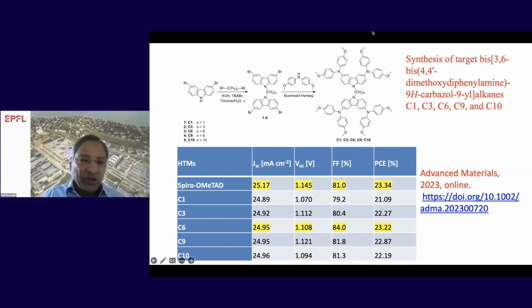That was the idea. So here we have changed the chain length of the two carbazole containing units from C1. The reference sample always gives very high efficiency, 23.34. That's spiro-OMeTAD as a reference sample for us. The C1 link between these two carbazole units gives a 21% efficiency. If we increase the carbon length from C1 to C3, the efficiency increases to 22.27. From C3 to C6, the efficiency increases to 23.22.